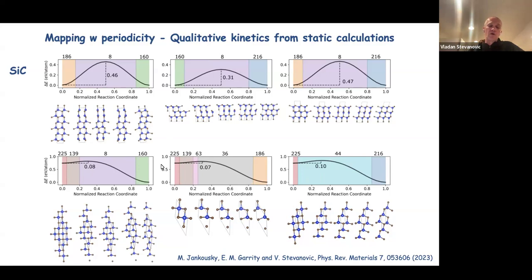In the literature's qualitative discussions of these so-called bulk barriers, 100 millivolts is usually used as a rule of thumb for distinguishing whether something is going to be slow or fast in terms of the kinetics of the transformation. So this picture reproduces fairly well the known experimental fact that the high pressure phase, which is rock salt, once you release the pressure, is going to live very short and transform quickly into the other ones, whereas the tetrahedrally coordinated ones are going to live long. And the upper ones are actual metastable phases.